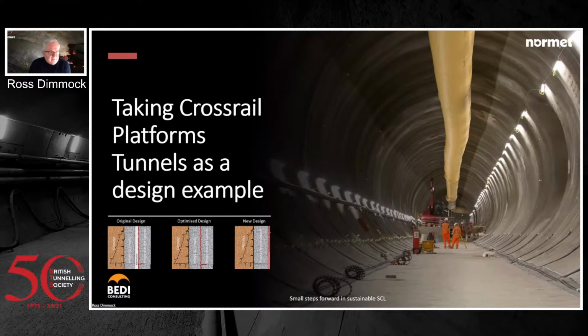Interestingly, we did a quick exercise with BEDI Consulting. We went back to Crossrail and looked at the platform tunnels again with some different lining configurations and different materials. We looked at the original design, as you see on the left, down the bottom left, and in the middle, an optimized design where we took out regulating layers and just put a membrane. So we're looking at a new kind of membrane that we could use there and take out the complexity of all these different layers, try and make it three. And then where we'd like to go is a much simpler spray concrete tunnel lining of one big structural waterproof lining with a waterproof catch-all, umbrella, membrane, mortar, whatever you like to call it, on the inside.